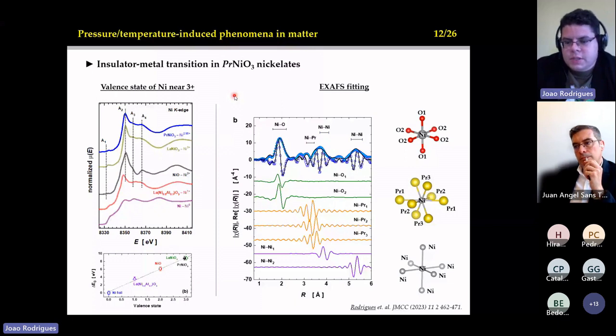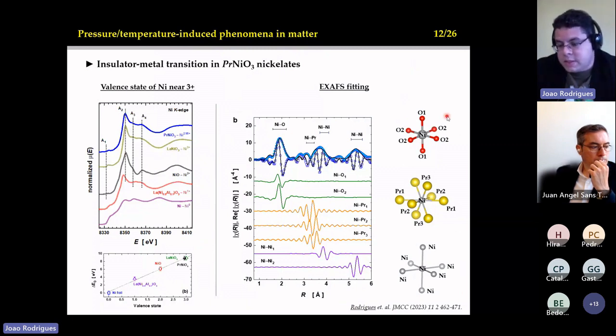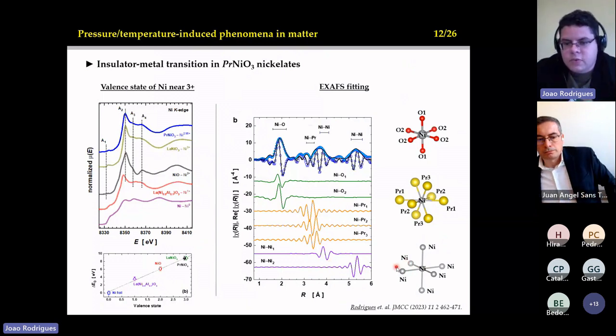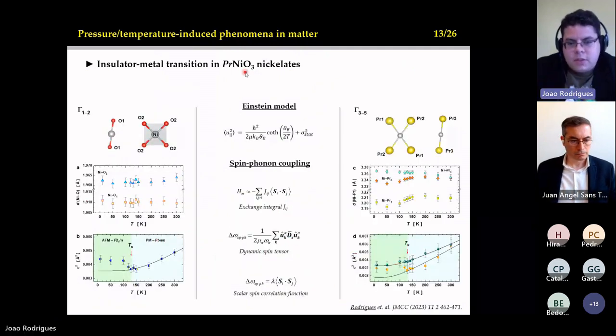And then we started to investigate the local structure using XAFS. Okay, this is an example of the oscillation XAFS already transformed using the fast Fourier transform. And then we create a structural model, which is already reported here, a model that describes the local structure around the nickel atom, which is very important for the insulator-metal transition. And also the outer shells, which is the interaction between nickel and praseodymium, and the very outer shell, which is the interaction between nickel and nickel, at around 4 to 5 angstroms, very far from the nucleus.